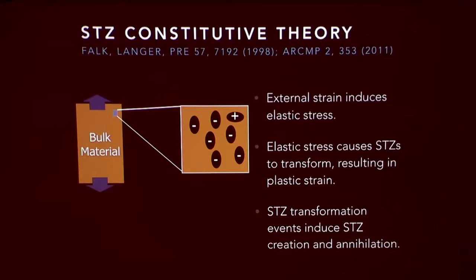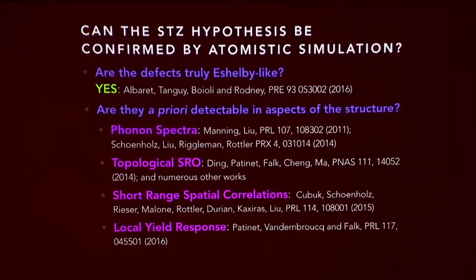But also in the process, there's plastic work being done, so some end up getting annihilated and others are created in regions that previously weren't deformable. So that was the picture that we had used to develop this constitutive theory, and I'll talk more about it later, but it all hinges on the existence of these local point defects controlling the deformation. So one big question in this field is, can this hypothesis, that deformation in glassy materials is controlled by point defects of this kind, be confirmed by atomistic simulation?